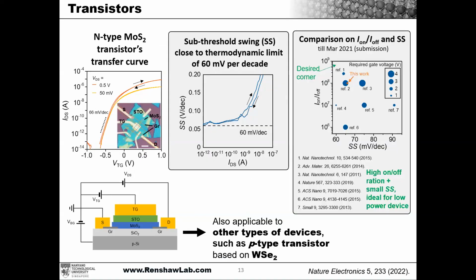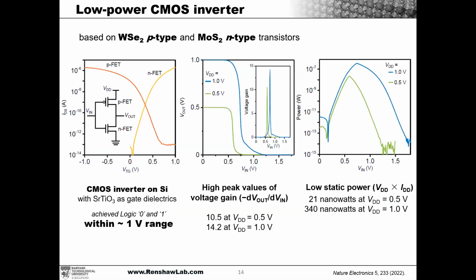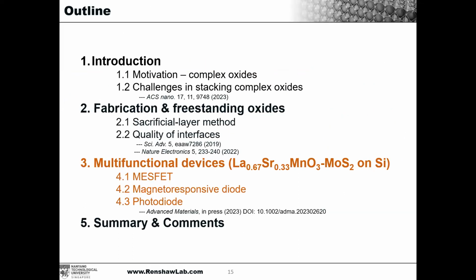So we achieved a transistor. We combined strontium titanate and MoS2, and we can fabricate a high performance transistor. It has a very good subthreshold swing, meaning very good energy efficiency, and also a very good on-off ratio. So it's kind of state of the art. On top of that, this technique is also applicable to other combinations. This is the demonstration that we can apply the technique not only to MoS2, which is N-type, but also to the P-type WSe2, giving P-type semiconductor transistors. Then, of course, using the P and N transistors, we can build an inverter, and the energy efficiency is very good. So this is about the fabrication, what we do.